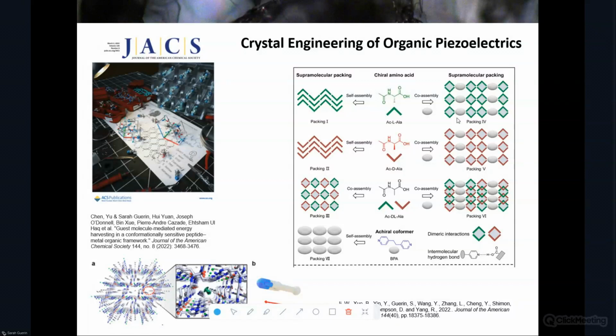This particular study was also fun because it was our first metal organic framework study, and we used our DFT models to validate what our collaborators saw, which was that if you have a MOF where you can switch the guest solvent, then the dipole moment of the solvent, if it's orientated in the correct way, can modulate the piezoelectric response for the same ligand, the same MOF with the same ion. So really lovely, where we show that acetonitrile, because of its dipole moment, maximizes the piezoelectricity while keeping the chemistry of the metal organic framework itself constant. So really fun bit of crystal engineering there.